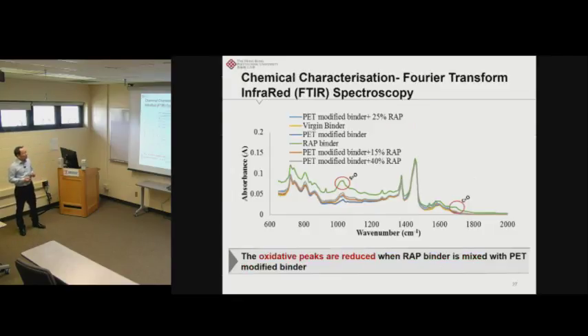We also conducted the FTIR test on different binder samples. This green one represents the binder extracted from the wrap mixture, which is aged binder. For the aged binder, this one on the top, we can clearly see two peaks. One corresponds to the SO double bond, and the other one corresponds to the CO double bond. These two peaks are mainly due to the oxidation of the binder.